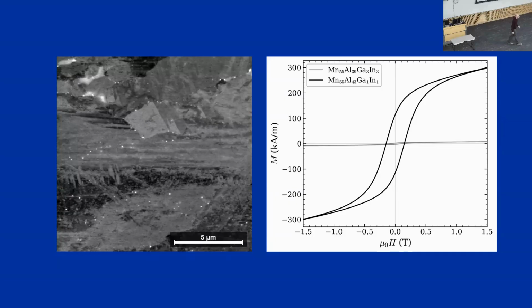And on the left, you'll see the SEM micrograph that shows you those little spheres that are in there, right? In the white, you see those bright regions? Those are little nanoprecipitates of indium, which act as friction for the motion of the domain walls and increase the width. So we're really excited about this.